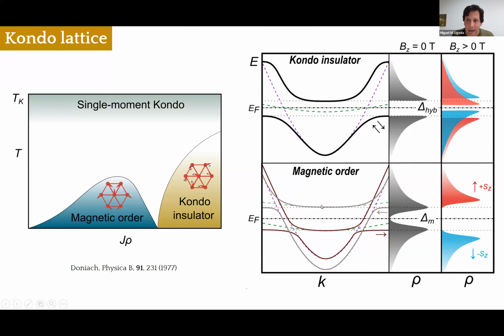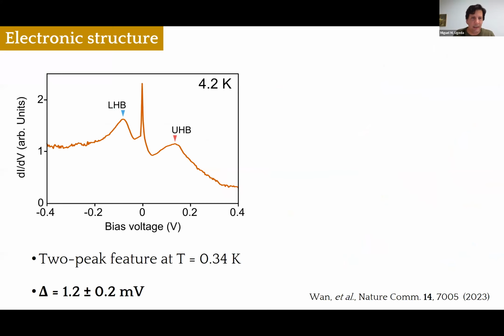So if we apply a magnetic field, in principle, these peaks should split into two here in the conduction band and in the valence band, whereas in the magnetic order case, there should be just one relative displacement between the peaks due to the Zeeman effect, but no new structure should show up. So there's one way to distinguish between these two ground states. So this is what I did.